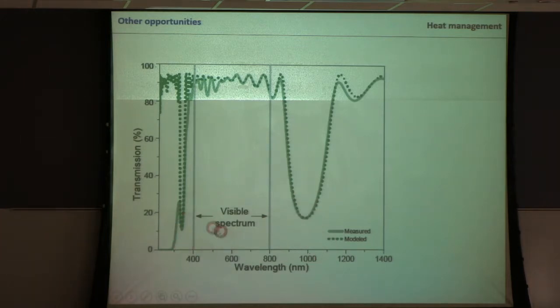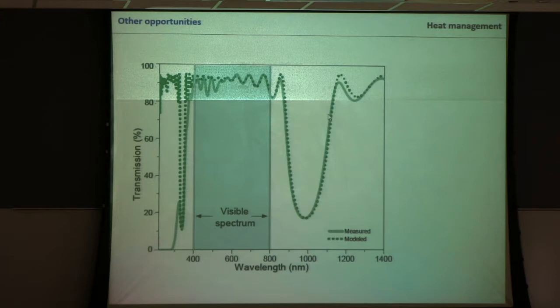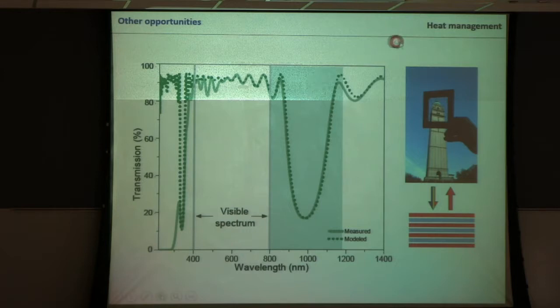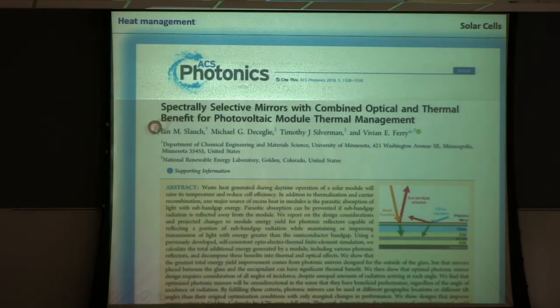But you see here very nicely that our mirror is very open in the visible, and it reflects in the near-infrared. The visible is very open, so the solar cell actually can absorb the light. And here's a picture. I have one in my office. Trust me, there is a multi-layer film in there, so it's really fully transparent. So we aim now to work with NREL to incorporate them not only in the organic solar cell, where it's relatively easy because we process them all from solution, but really try to also integrate them in inorganics.